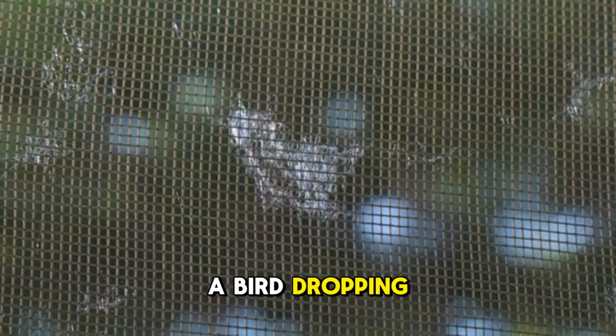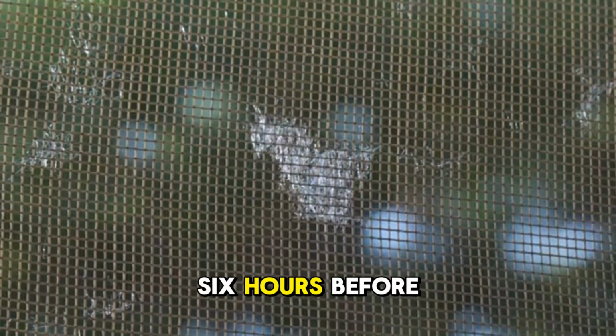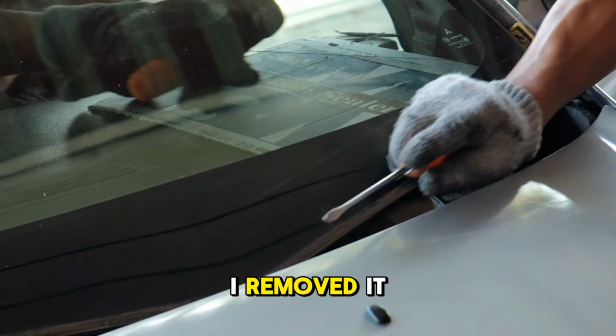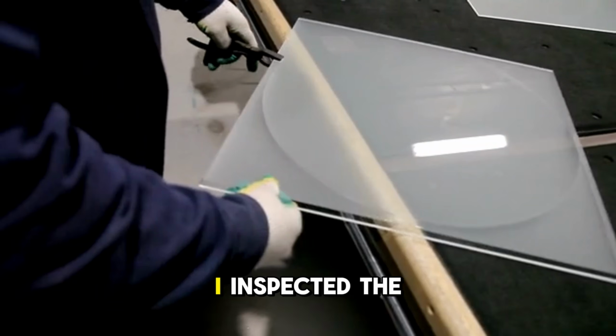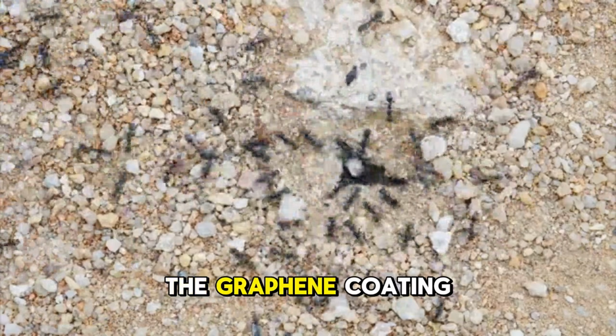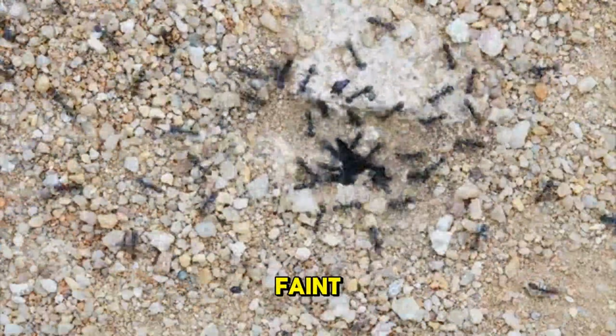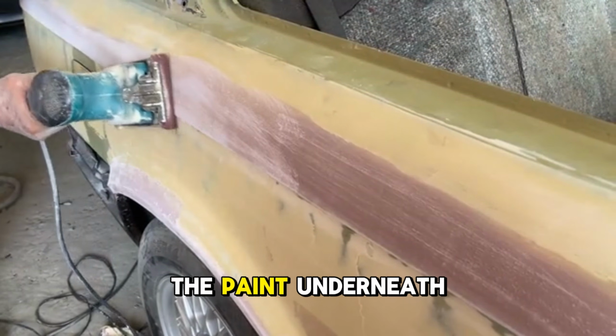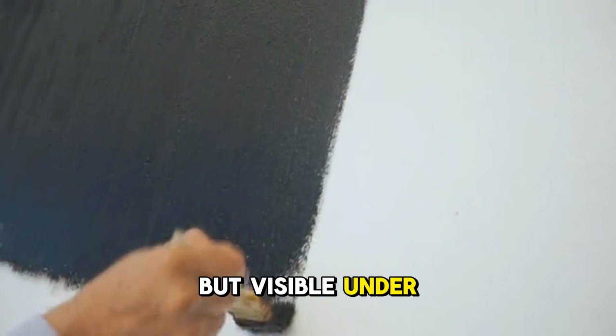A bird dropping sat on the graphene panel for 6 hours before I noticed it. I removed it with a damp cloth. I inspected the panel under a light. The graphene coating at 4 months showed a faint etch mark where the dropping had sat, not deep, not damaging to the paint underneath, but visible under direct light.